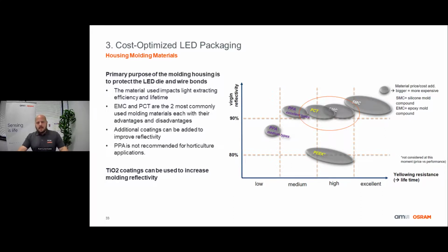PCT offers slightly better reflectivity than EMC and at a lower cost. Now, while PCT is less resistant to yellowing, it's a very mature material, and it has improved greatly over time. Today's best PCT materials easily match, if not exceed, the performance of EMC materials of the past. Coatings like titanium dioxide can also be used on the inner walls to increase reflectivity. Some LED manufacturers may choose to use lower quality thermoplastics like PPA in order to keep costs down. I don't recommend selecting an LED that uses PPA for horticulture applications or for any professional lighting application, as they exhibit extremely poor photo and thermal stability characteristics.